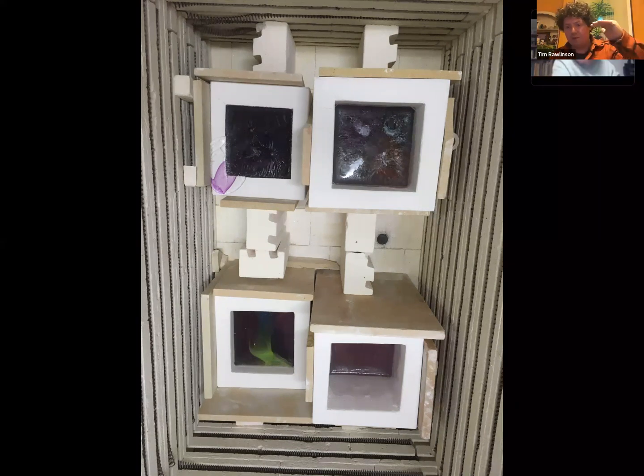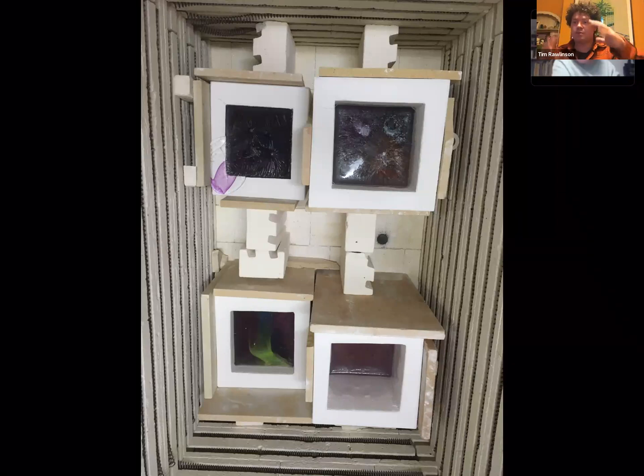Once it's reached molten temperature, it will then move and change. Depending on the piece, that might only be for a couple of hours. Any more than that, and the color will just move too much. It'll only be a couple of hours at very hot temperature, and then it will drop down to about 500 degrees, which is the annealing temperature for blown glass.